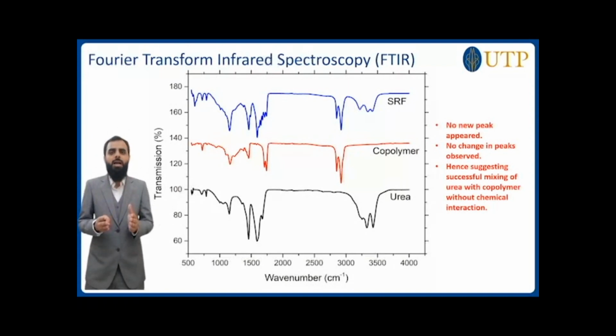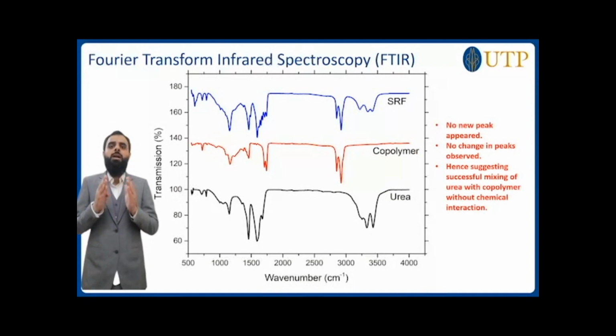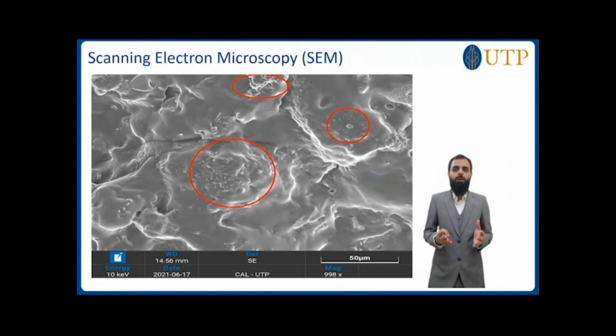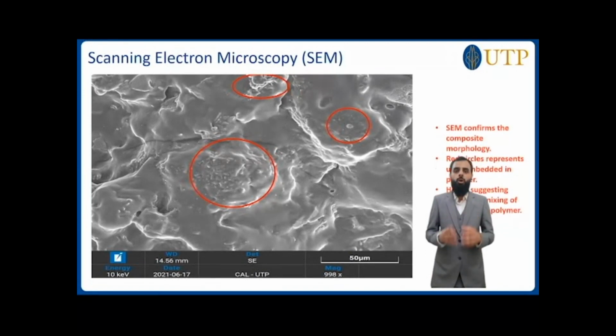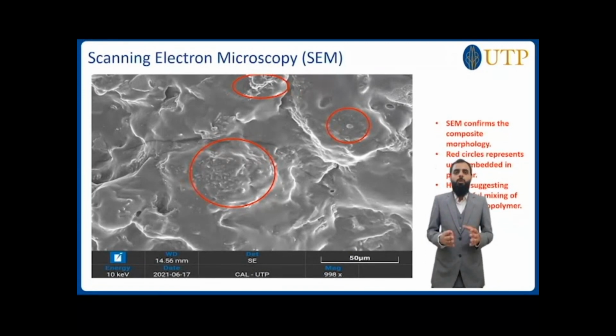The only reaction has occurred between the sulfur and rubber seed oil, which is evident from the appearance of CH stretching in the spectrum of the fertilizer, which confirms the formation of the fertilizer composite and also the physical interaction of the urea. The SEM micrograph shown revealed the composite morphology of the produced fertilizer. The red circle represents the urea particle embedded within the structure of the polymer. It also confirms the uniform distribution of the urea particle over and within the fertilizer.